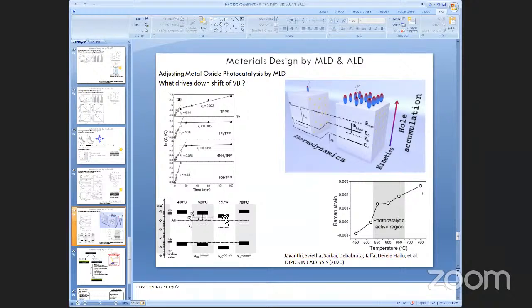states. When you anneal it at higher temperatures, you increase the crystallinity of the system. I did not show it, but at higher temperature, you get larger and more crystalline structures. But you also start at a certain point to have a phase transition from anatase to rutile, and all of this together changes the system again. So to get efficient photocatalysis in our system, which is quite different from other titanium dioxide systems, the optimum is to have it annealed at this region.